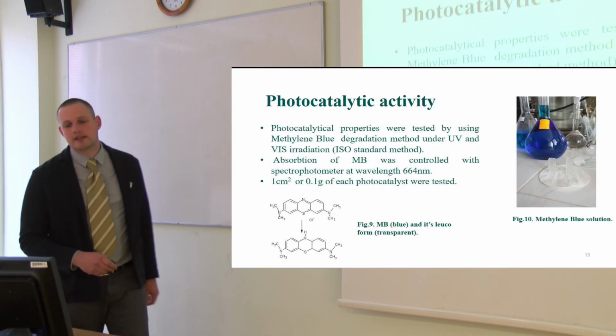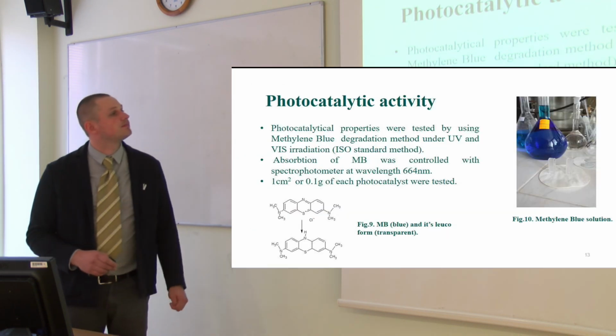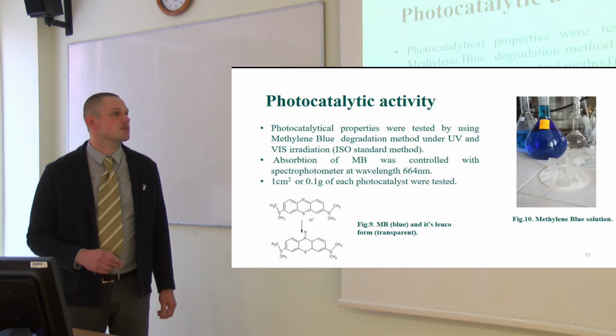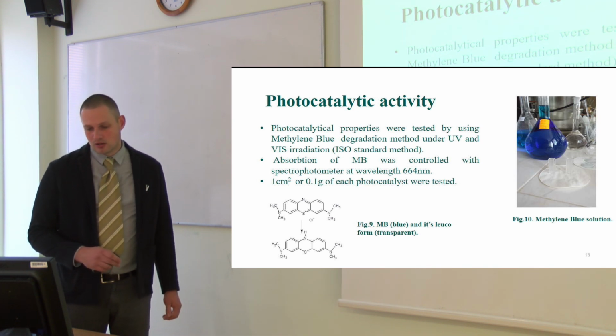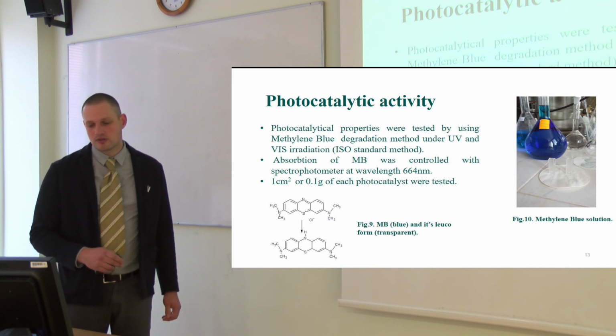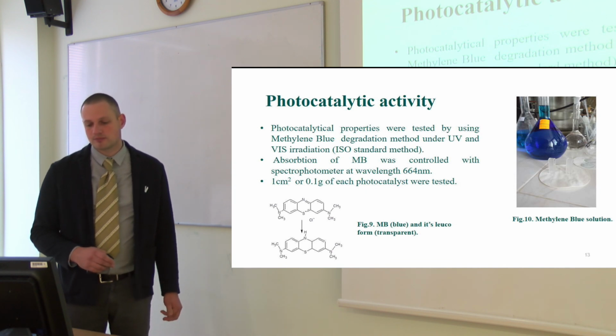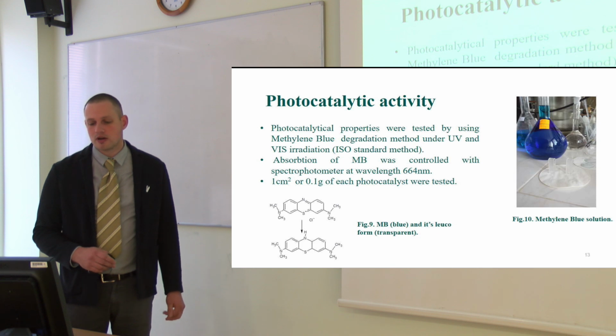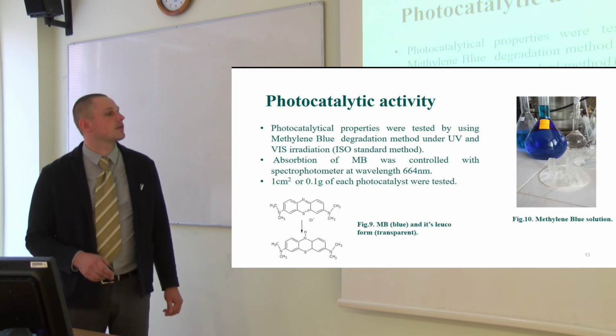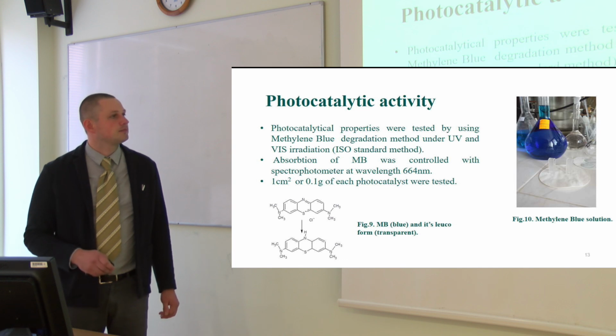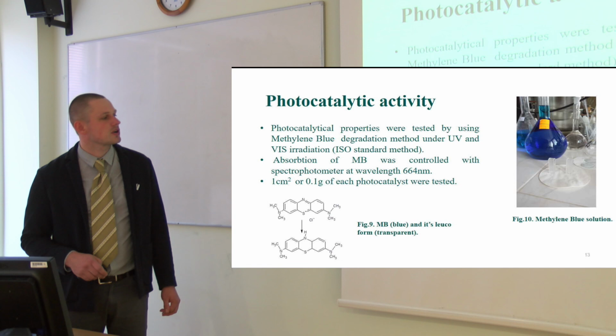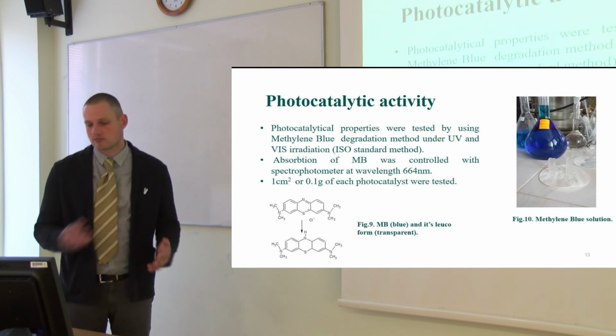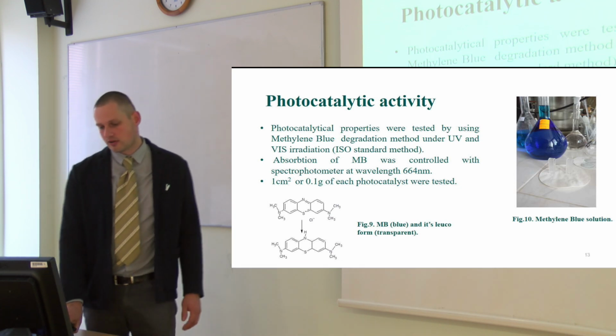So the photocatalytic activity was measured by using methylene blue degradation method. It is an ISO standard method. So the absorption is controlled with spectrophotometer at the wavelength of 664 nanometers. And during this process, such a blue solution becomes transparent, and we can calculate the concentration of it.